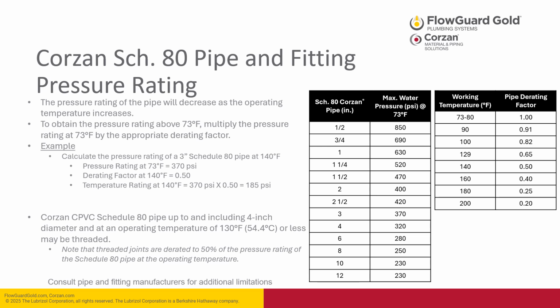Corzan CPVC Schedule 80 pipe up to and including 4-inch diameter and at an operating temperature of 130 degrees Fahrenheit or less may be threaded. Note that threaded joints are derated to 50% of the pressure rating of the pipe at the operating temperature. Make sure to consult your pipe and fitting manufacturers for additional limitations.